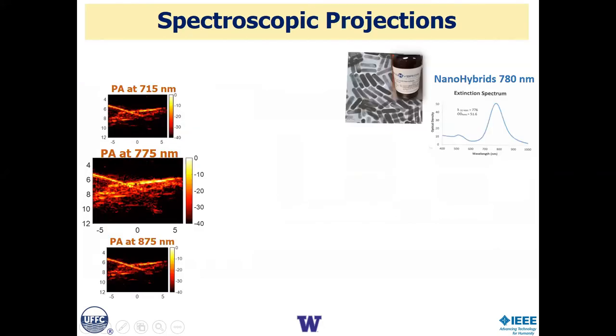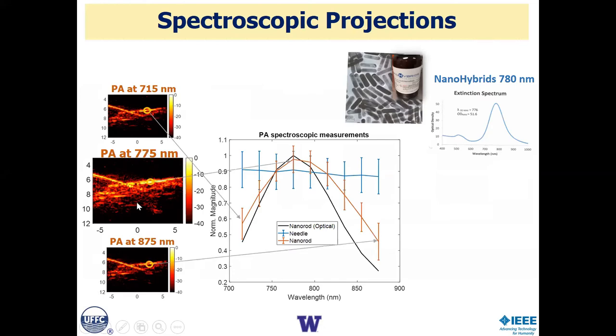Okay, when we do that, after we've space and time registered the photoacoustic images, which in this case, since it's a tabletop experiment, there's no motion, so the motion compensation isn't important, but the fluence compensation is, and that's been done here. So now when we look at an individual pixel, say in this area here, we can, for the different wavelengths at that one pixel, map out its optical absorption spectrum.